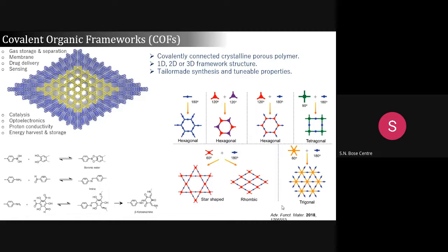So these are the basic chemistry. This is the first chemistry used, where boronic acid condenses with the catechol kind of system, and then boronic ester forms, and it can form a crystalline framework. But this is very much susceptible towards water. If you calculate the delta H for this reaction, it is zero. Basically, there is no change in the delta H during this reaction. So this kind of linkages are not very stable.